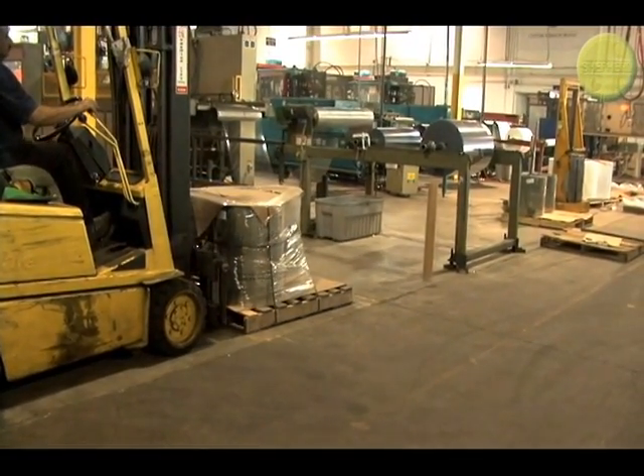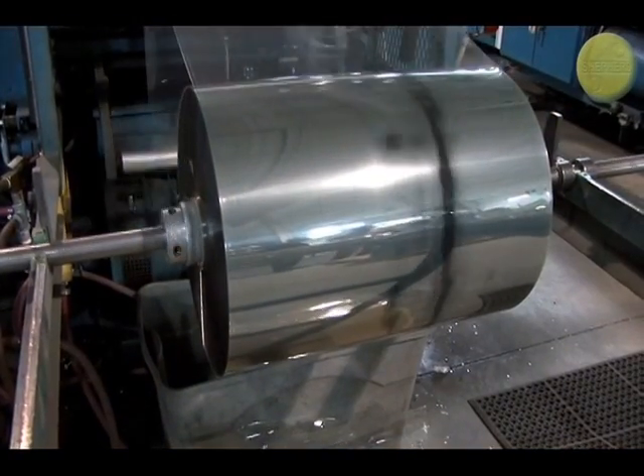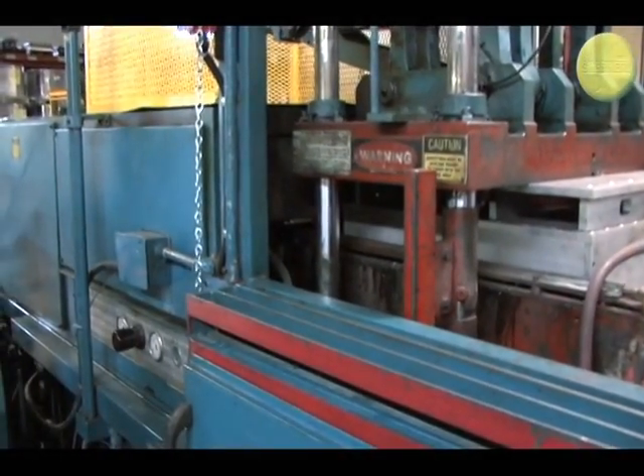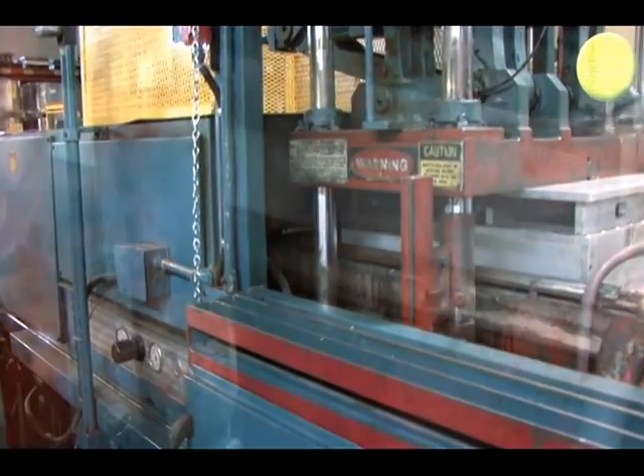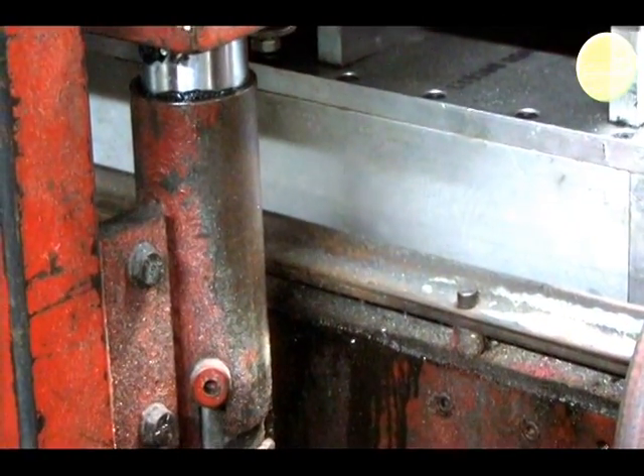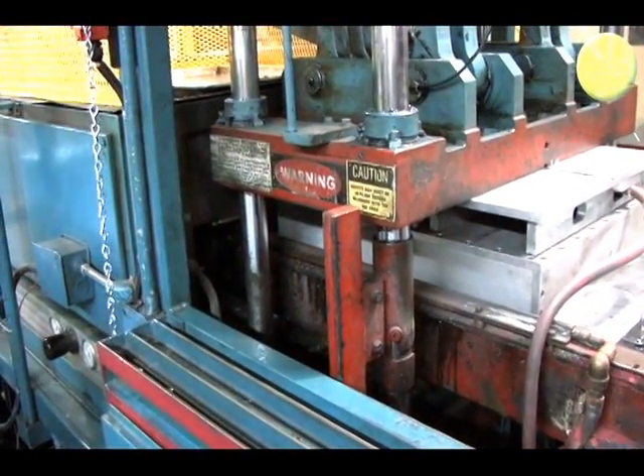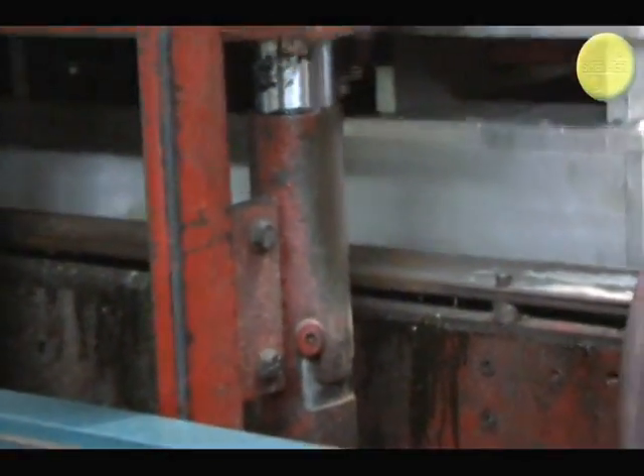The new rolls arrive and are placed on the production machines. The plastic is fed into a hot oven, where it is heated up to the point of melting. It then feeds out, where it droops over the waiting mold. Vacuum pressure is applied, sucking the hot material into the tool, and a plug assist drops down to further aid in the forming of the product. The tool stays closed momentarily to allow the product to cool, then it is released, and another hot sheet takes its place.